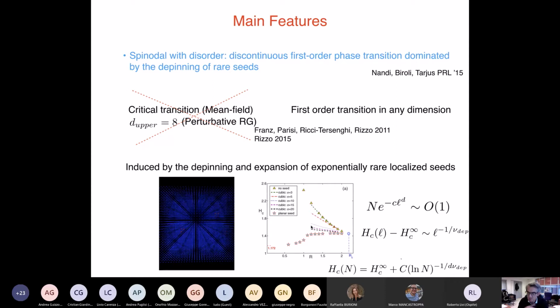So it's exactly what I was saying to you. If I have a big seed, a big seed will fail before the small seed. And so the phase transition will be due to extremely large seeds that are embedded in the other phase. And the way to understand this, this curve is going down. This line, which is here, corresponds to the depinning transition of an infinitely large seed.